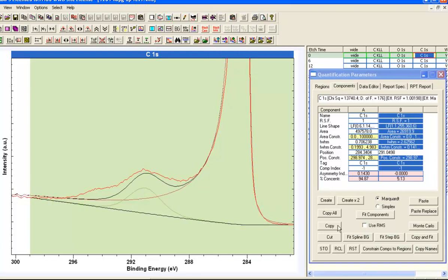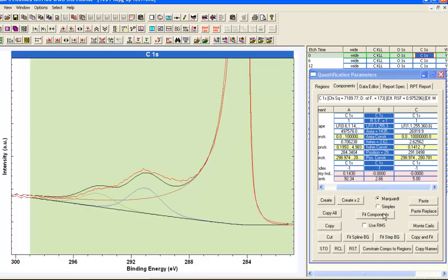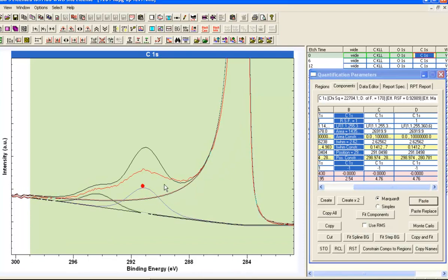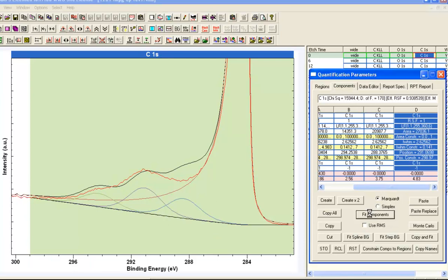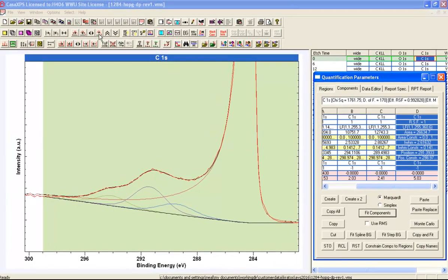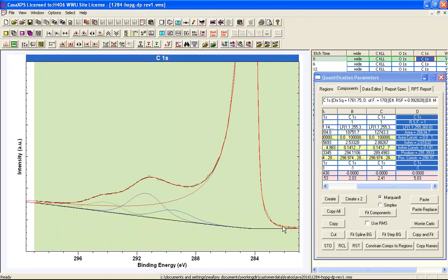And what I'm going to do now is copy it and put 3 peaks in here by taking copies of this peak that I've just set up the limits to. And if I say fit, I end up with a peak fit to these data. So while the data appear to be fitting quite nicely, the actual asymmetry that is introduced here is really quite difficult to assess. And you can see that it actually extends a little bit too far out here.